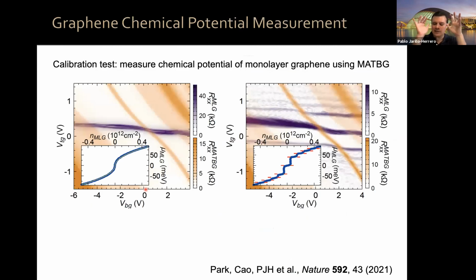Magic angle bilayer graphene is a complicated object. Let's make sure we can use the scheme to measure monolayer graphene, where we know what the answer should be. So we're going to measure the chemical potential of the monolayer graphene using magic angle bilayer graphene first. What you can see here are the resistivity of the monolayer graphene in purple and the resistivity of the magic angle bilayer graphene in orange. If we track the charge neutrality of the magic angle bilayer graphene, this is giving us, through the equation that I showed earlier, the chemical potential of the monolayer graphene.